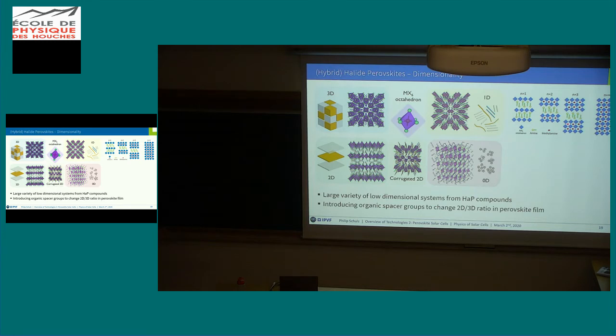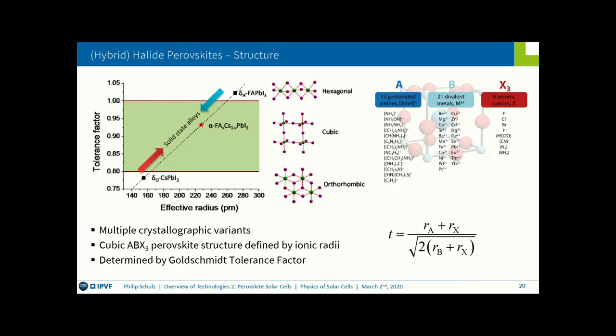There are also mixtures in between where you can, for instance, start with your MX6 octahedron and have methylamine, the small molecule, and a longer chained amine, and depending on the mixing ratios, you get a 2D-3D mixed perovskite with its own particular optoelectronic properties, and also some sort of a superstructure, assuming some structuring guidelines given by the chosen amine. So if, for instance, the molecules stand like this or shifted by 1/2 cell from each other.